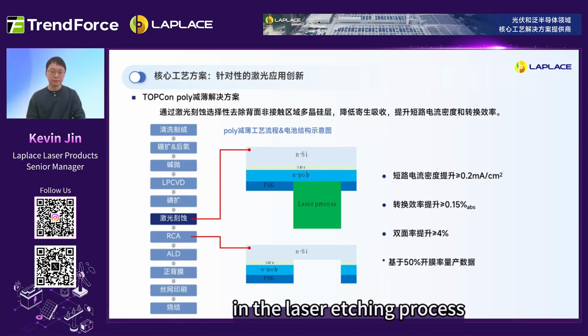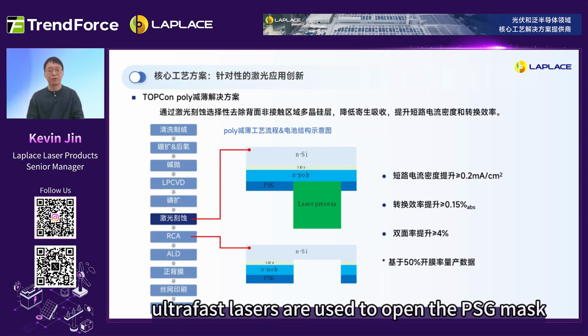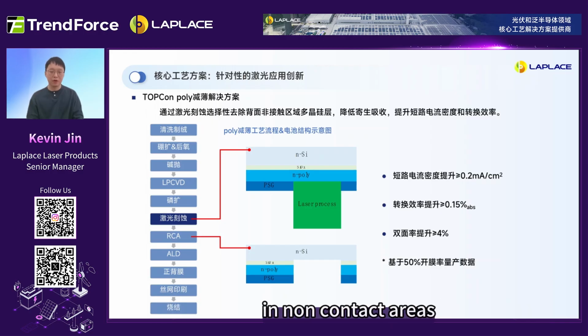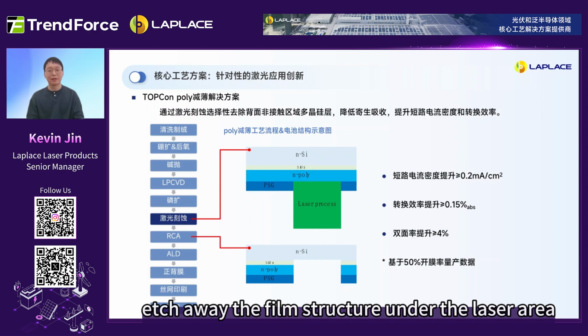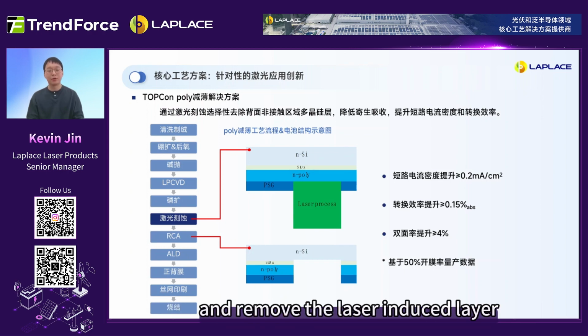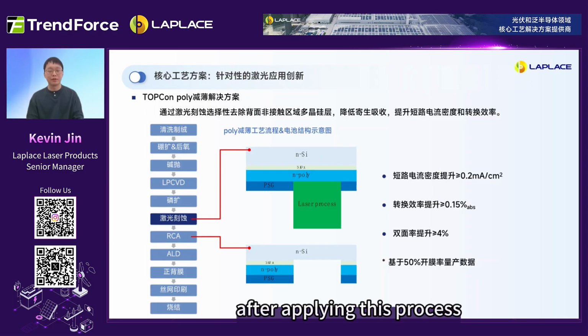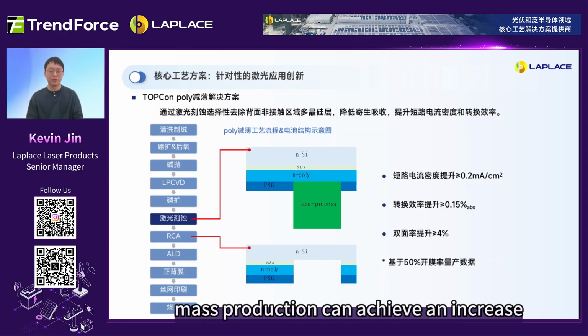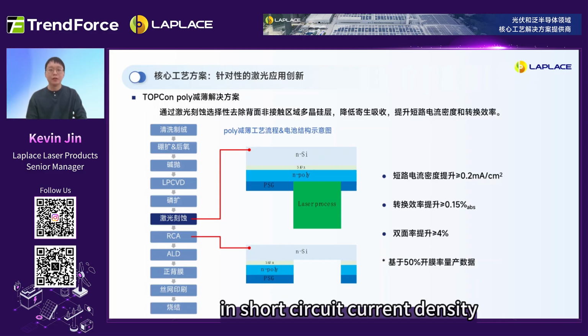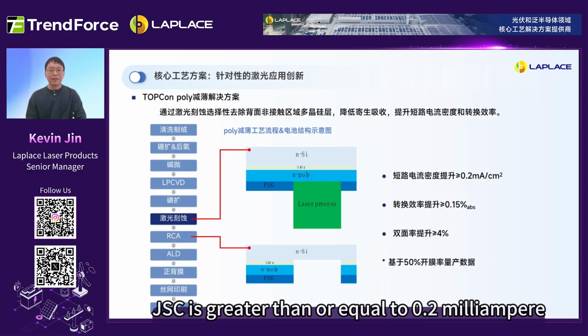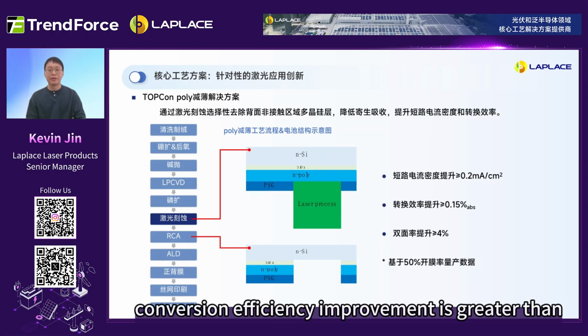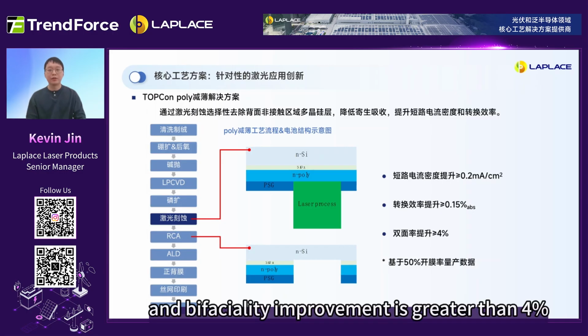In the laser etching process, ultra-fast lasers are used to open the PSG mask in non-contact areas. Then, subsequent wet processes etch away the film structure under the laser area and remove the laser-induced layer, forming a patterned effect. After applying this process, mass production can achieve an increase in short-circuit current density, JSC, greater than or equal to 0.2 milliamperes per square centimeter. Conversion efficiency improvement is greater than 0.15%, and bifaciality improvement is greater than 4%.